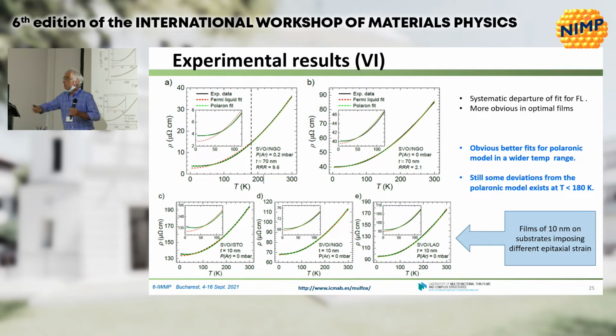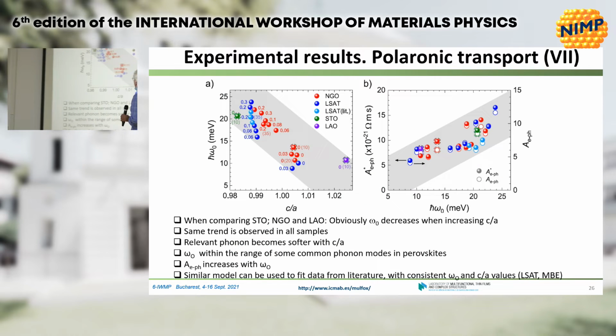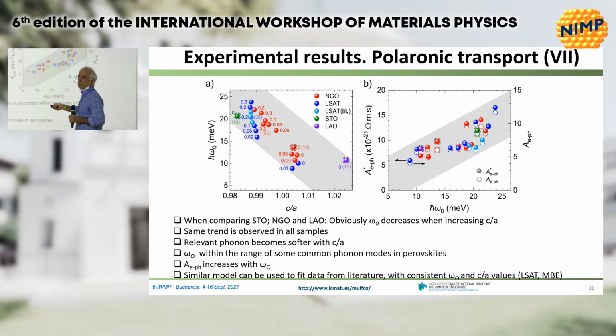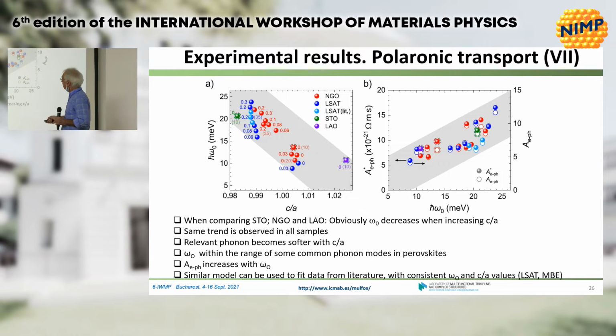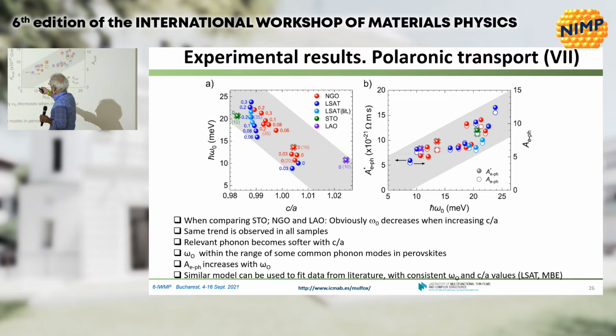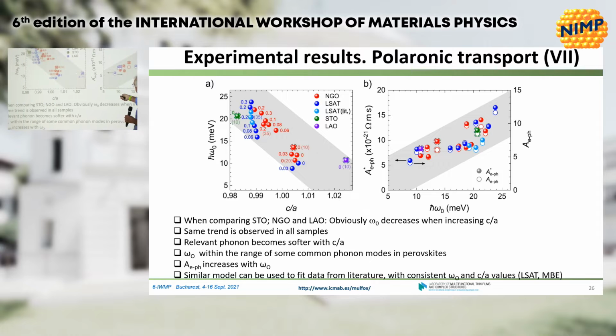So the substrates maybe impose a different strain or whatever. Maybe the phonon is different. So this is the phonon frequency as a function of the distortion of the lattice parameter measured by X-ray. And you see that all the data fall approximately on this line. And here there are data from films made in Barcelona and also films taken from the literature, these points here. And the films that I was describing before, the same things on different films, this green, this blue, and this red. Those are the omega 0.